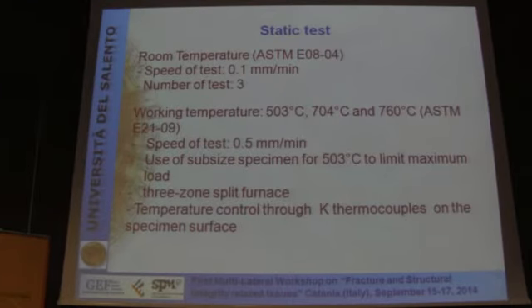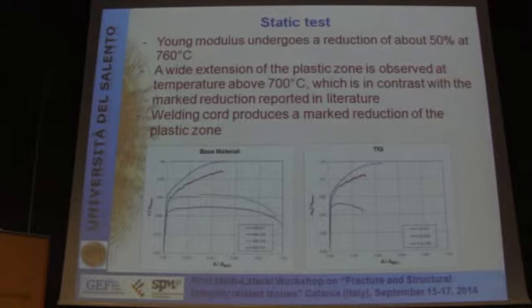Heating was obtained by a three-zone split furnace, and the temperature was controlled by K-type thermocouples located on the specimen surface. These are the results of the static test for base material and TIG welded material. The presence of the welding bead dramatically reduced the elongation to failure. Other properties are practically similar.